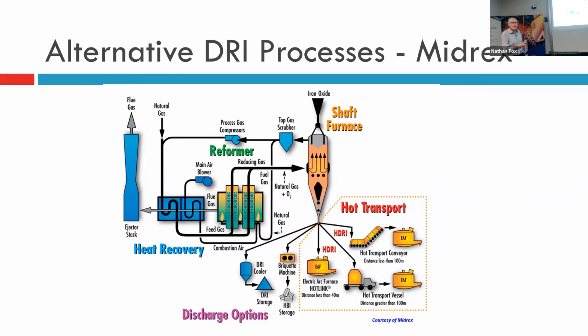The product you get from the shaft kiln will oxidize. The pellets actually stay in the pellet shape, but they're porous. And because you've got fine iron particles in there, iron will burn as soon as it's exposed to air. So you either have to put it into your electric arc furnace straight away, or you briquette it, so that you push the particles of iron together so they're less likely to react with oxygen. And so that's where the HBI part of it comes in.